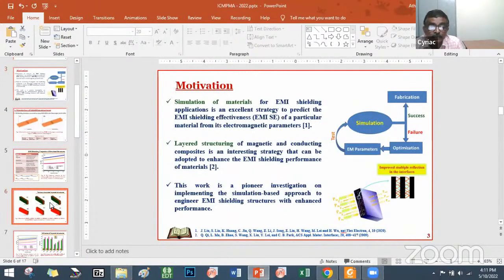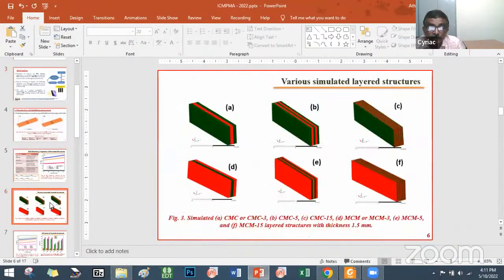So we were wondering what will happen if the number of layers increases. We are giving more interfaces to reflect, and thereby more absorption of the electromagnetic radiation. That's why we have incorporated a definite thickness only. All these materials have a thickness of 1.5 mm. However, we have reduced only the thickness of the individual layers. With 3 layers, each layer has 0.5 mm thickness. When we increase the number of layers to 5, the thickness is reduced to 0.3 mm. And this happens in all the materials.